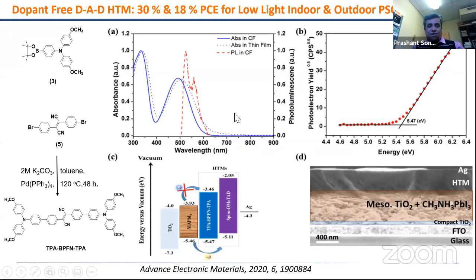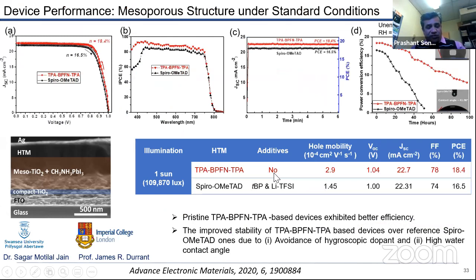Usually, for all of the materials, we do optical absorption, where we calculate the band gap by taking cutoff values. Then we get the HOMO value by PESA, 5.47, and looking at 5.47 of this HTM with Spiro comparison, and LUMO. We get the cross section of this standard mesoporous device. Again, using this dicyano device without having any additives, these all are dopant-free devices.